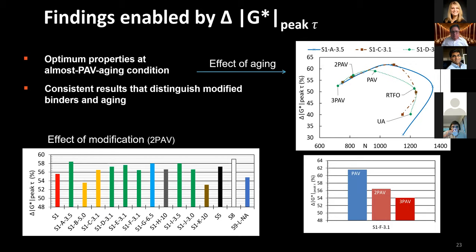So some of the findings that were enabled by the new criteria of delta G is that you could optimize properties at post-PAV aging conditions. You could adequately define the effect of aging. As you can see by the graph on the right-hand side of the slide, you've got the unaged binder, the RTFO aged binder, single PAV, double PAV, and three PAV. We saw consistent results that distinguished the modifiers and the aging.